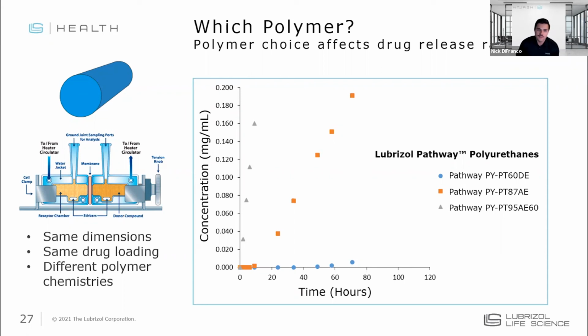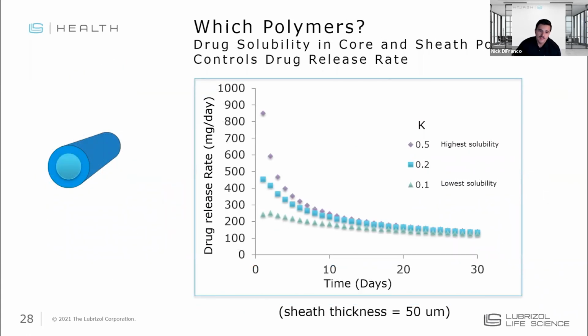And so what this really goes to show is that just by changing polymer selection, you can have a significant impact on drug release. And if you think about tuning the release of a product, it's possible that by changing those ratios or those chemistries, you can fill in this white space and hit targets that are in between these three curves. So understanding the different levers you can pull on the chemistry is important, but of course, the way that the polymers interact with the API is also very important in designing these systems.